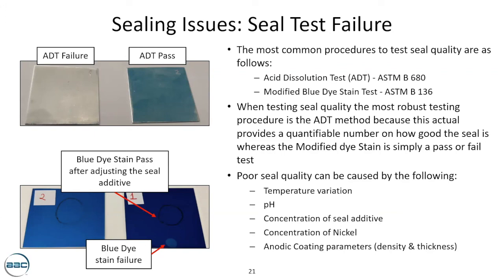Now, it can happen that, for example, you have two parts that have been processed on the same rack, but one of the parts passed the dye stain test and the other one did not. In this case, we should use an acid dissolution test, which will actually tell us what the real reason is, because it could be that the part that did not pass the dye stain test had a lower coating density or thickness.